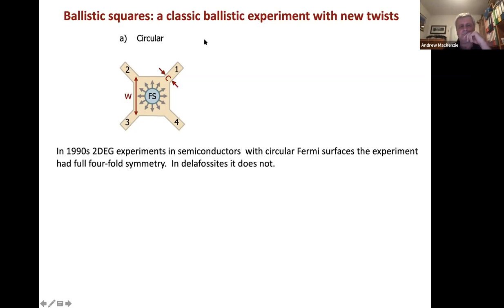And what that involved was taking either squares or crosses, where you've just broadened the diagonal current channels into a cross, and considering what happened when you attempted to run current, say, from 1 to 2 and measure voltages from 3 to 4. And because the current needs to bend to go from 1 to 2, a voltage measured in this way is called a bend resistance or a bend voltage in the jargon of the field.